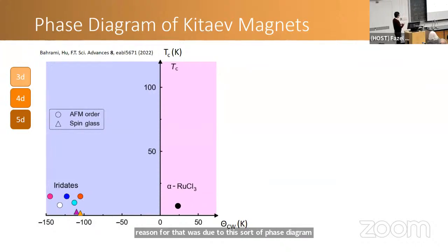Here I'm showing the magnetic transition temperature of these Kitaev magnets as a function of what we call the Curie-Weiss temperature. It's a temperature scale that we can deduce from magnetization measurements, and it approximately gives you the strength of magnetic interactions. So how strongly the magnetic moments or the spins interact, versus how high the ordering transition temperature is. That's the phase diagram. These iridate materials are all in this corner.